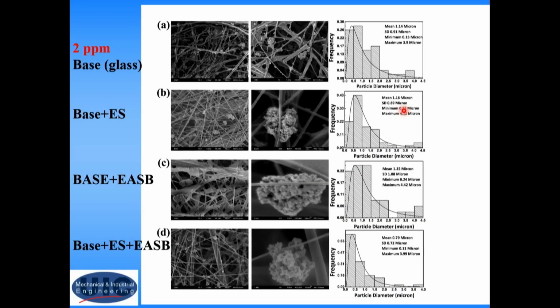Then we did some filtration experiments. So, the basic filter, glass fibers, I said cellulose, glass fibers, the basic one, then glass fibers with electrospun, and with supersonically blown. I'll concentrate on that. Interesting that you have collection of nanoparticles. In this case, the nanoparticles were copper particles, just for our detection purposes. It's easier to use copper particles on the scale of 100 nanometers. This is a very difficult scale to catch because neither diffusion nor inertial effects are effective in filtration. And what you see here is that most of the collected clusters are hanging on the thinnest fibers.